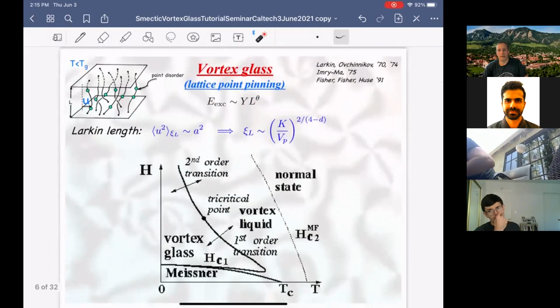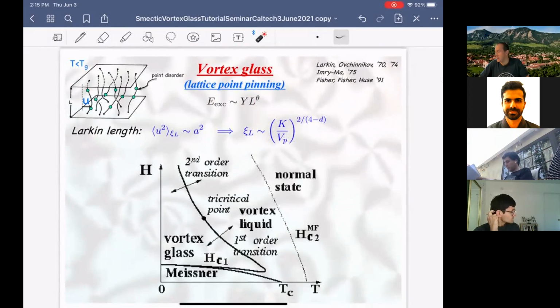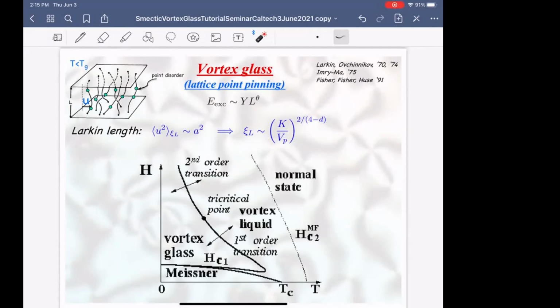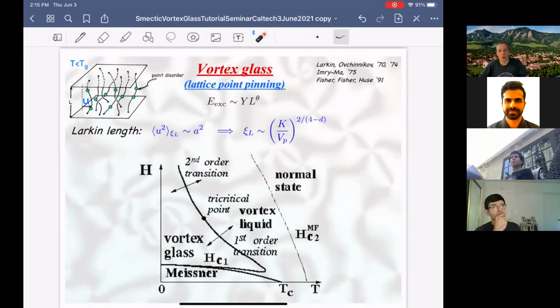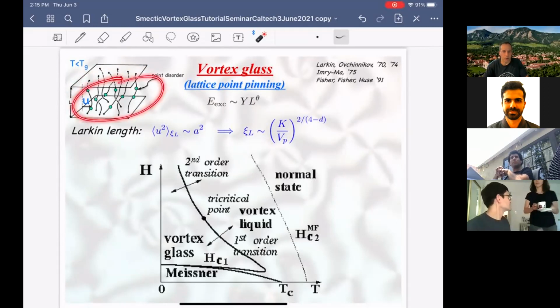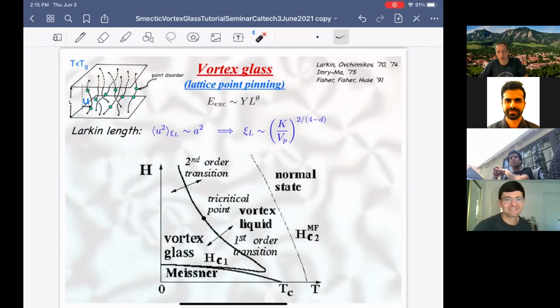But then, building up in complexity, one can move on to a more realistic situation. That's when these vortex phases are subjected to disorder, as any respectable condensed matter solid state system is. So you have all kinds of vacancies and interstitials in the actual atomic structure. You could also irradiate with electrons to create more impurities. And it's quite crucial for applications. It's also interesting from an intellectual point of view to explore how, even at zero temperature or low temperatures, this elastic medium, namely a vortex lattice, responds to a random pinning potential, which is how we think of these impurities or this point disorder, indicated in green circles.